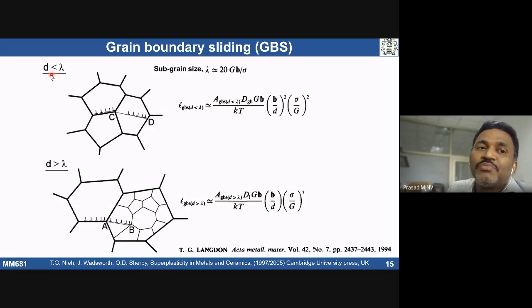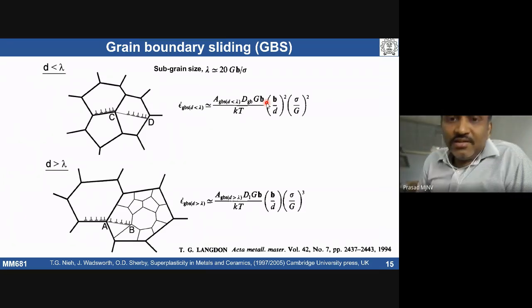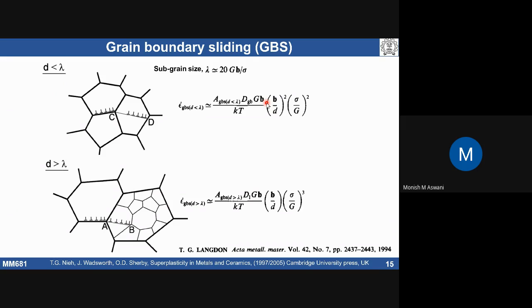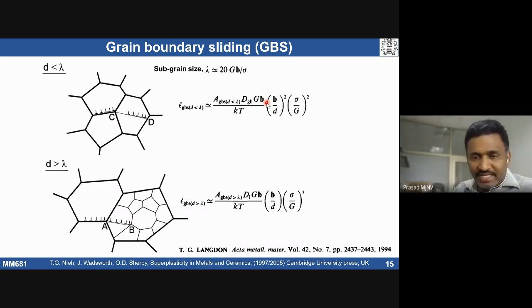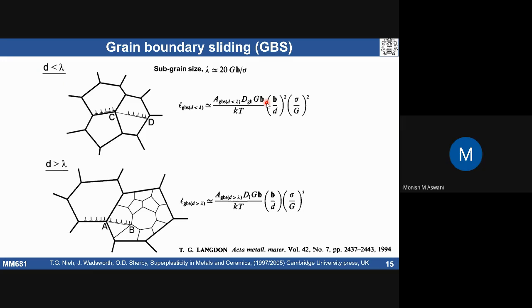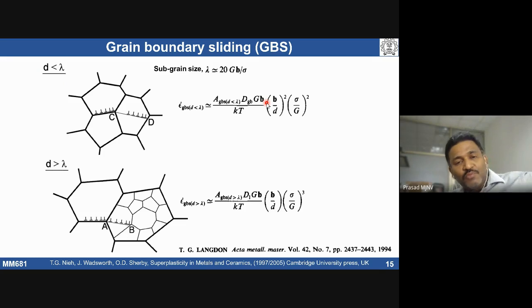Because if you talk about 1 micrometer, 2 micrometer, 5 micrometer grain structures, which basically follow this equation. But in both the cases, your cavity is getting accommodated by some creep mechanism, right? Yes, yes, so why is case 1 preferred over case 2? No, case 1 is not preferred over case 2. Both are going to happen.